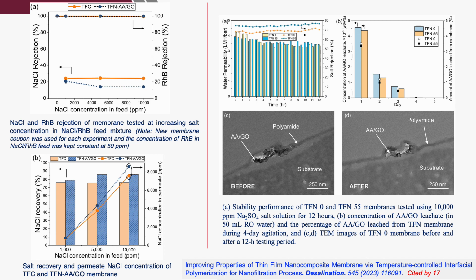We also tested the TFC and TFN AAGO membrane in the filtration process using feed solution containing NaCl and Rhodamine B. Regardless of the NaCl concentration in the feed solutions, both membranes can achieve very similar rejection, which is close to 100%. For the NaCl rejection, you can see here that our developed TFN AAGO membrane actually has a lower NaCl rejection, which is good because we want to recover the NaCl from the solution.